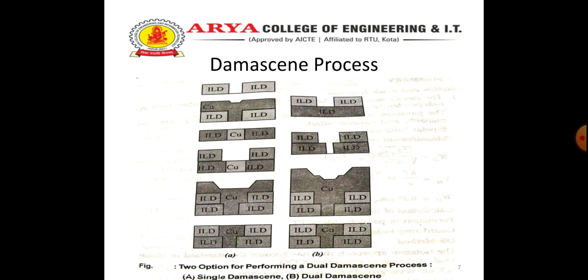Alternatively, both wire and line recesses can be done before copper deposition. This process has the disadvantage that the small feature wire must be patterned at the bottom of the interconnect recess, which for small wires can be extremely challenging. Copper can be deposited in a variety of ways.